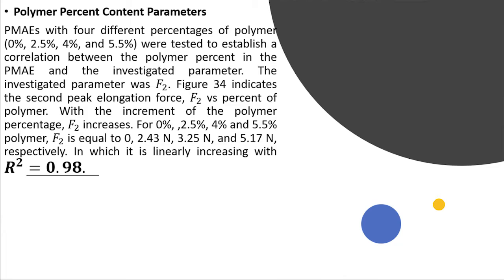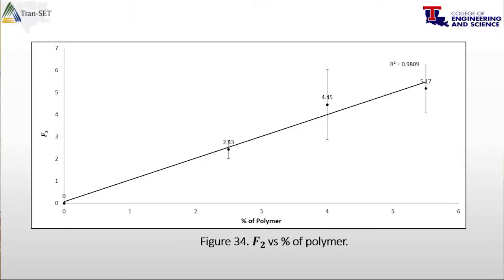And this is the polymer content. We have the results for different percentages of polymer as I showed you, and you can see that we have a good R-square value, but still we have some repeatability issues that we are working on, as you can see from the error bar. So we are still working on these.